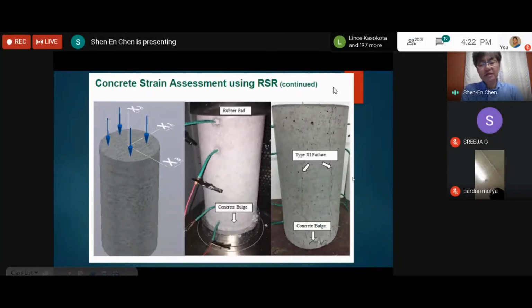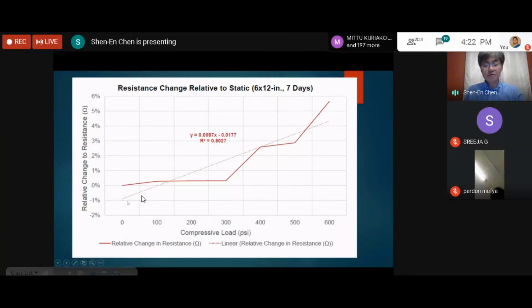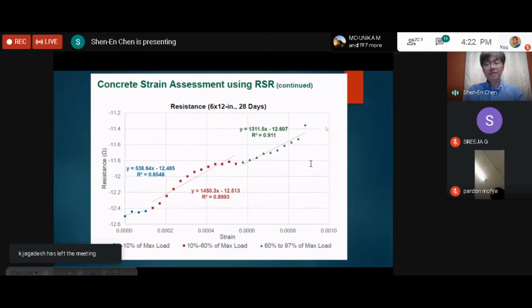We first start testing on standard concrete cylinders. So in order to measure the self-sensing component, we have to drill holes and then embed those copper wires to do the self-sensing. Okay, and then we do the standard compression test on those specimens. And as you can see, the resistance change is actually consistent with the compression load with some variation. And this variation is all material property dependent.